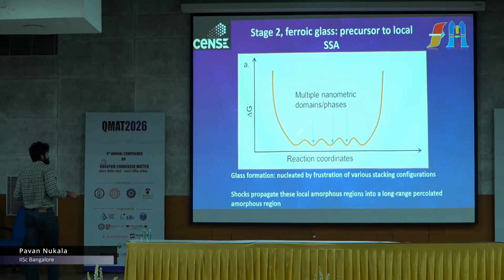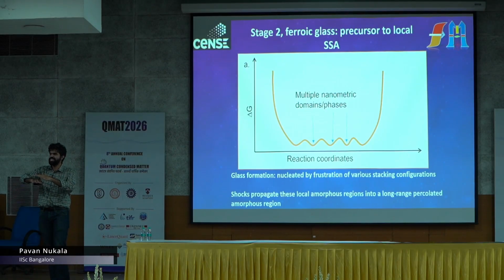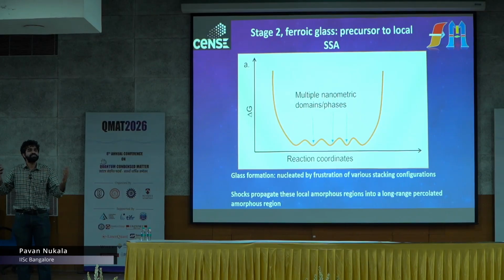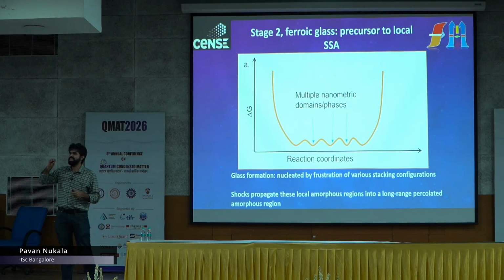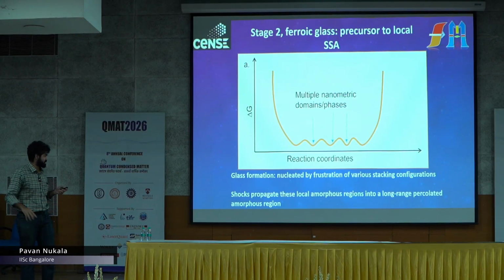All right. So essentially, because I can slide these layers so easily, and it's a thick material, I have various different configurations in which I can metastabilize indium selenide, right? Once locally I start creating these various configurations, it's like I punch holes into the wall, and after a certain hole density, defect density, the structure of the wall would collapse. Similarly, this gets frustrated, and locally I have an amorphization event. All right, but the surprise is that we see this amorphization over a long range. So it's not a local event; it's a long range event, right?